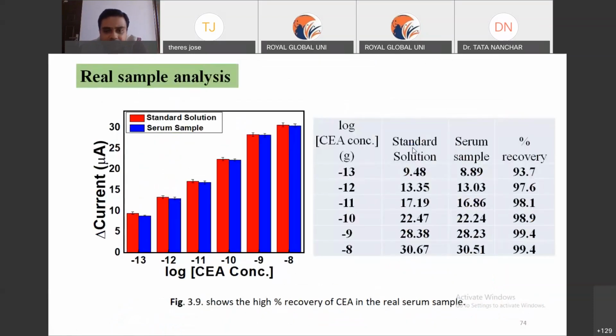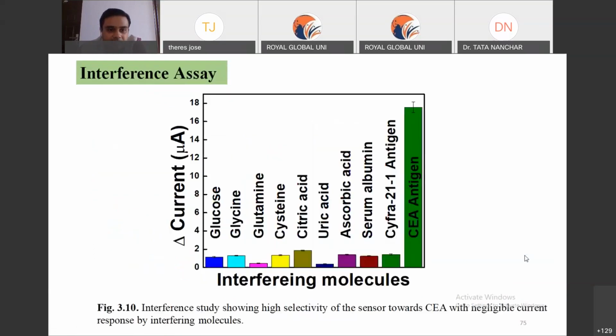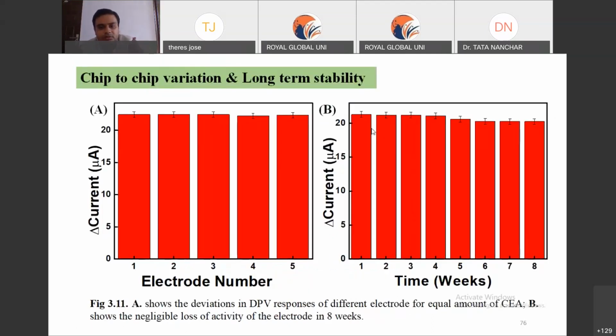This time we took the serum sample, because CEA is present in the serum. We can see the recovery of CEA in the matrix is quite good, about 93 to 99%. We can recover CEA when spiking it into standard serum samples. These are the interference tests. We again tested other cancer biomarkers, other proteins and small molecules all together to show that the developed sensor is highly robust and powerful. This is the chip-to-chip variation and the stability data.